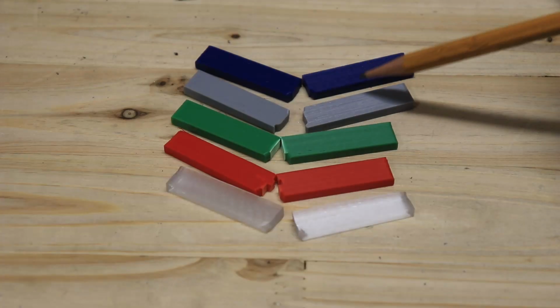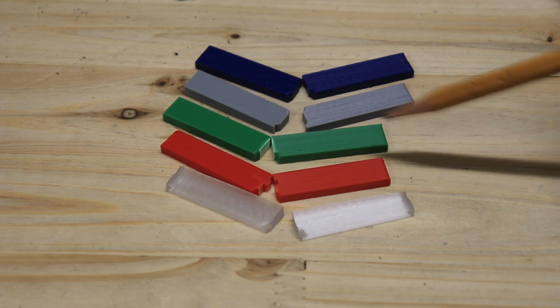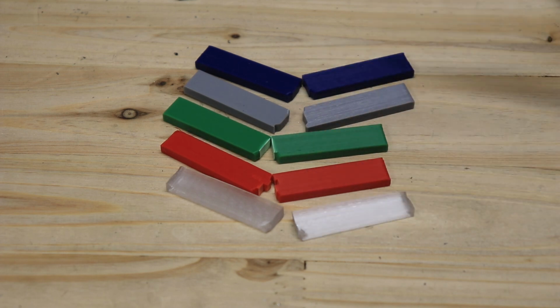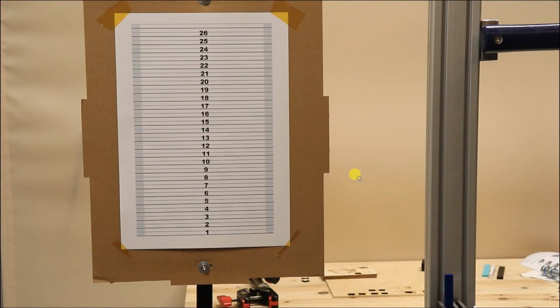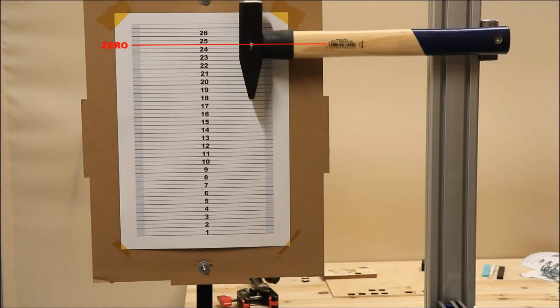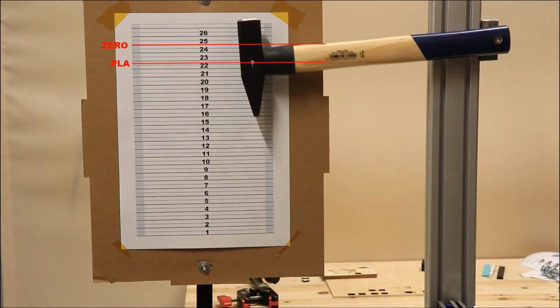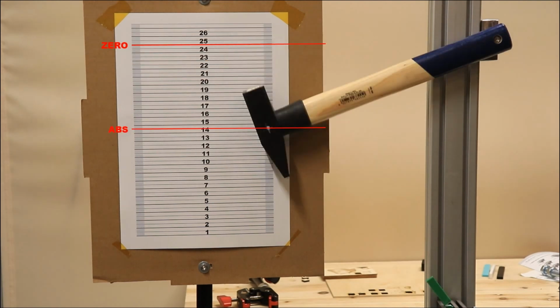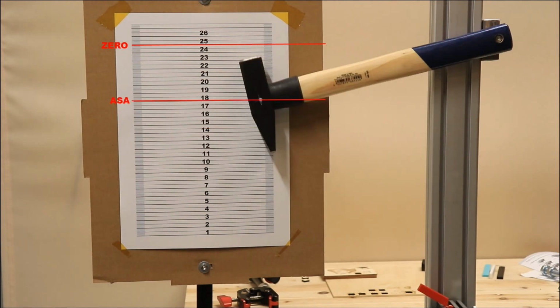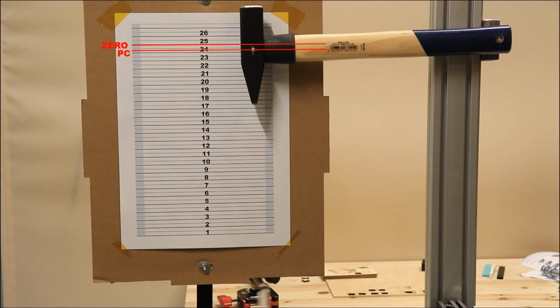And after this test I can see that ABS and ASA didn't break completely, but let's analyze the numbers and the images. This is the scale and this is the 0 position. This is after breaking the PLA test specimen, and very similar is the PETG. ABS was the strongest in this test, but also ASA was very strong too. And the most brittle is the PC, the polycarbonate. And this may be the main reason why you don't want to print, let's say, warranty-critical printed parts from polycarbonate, but from ABS as suggested by designers.